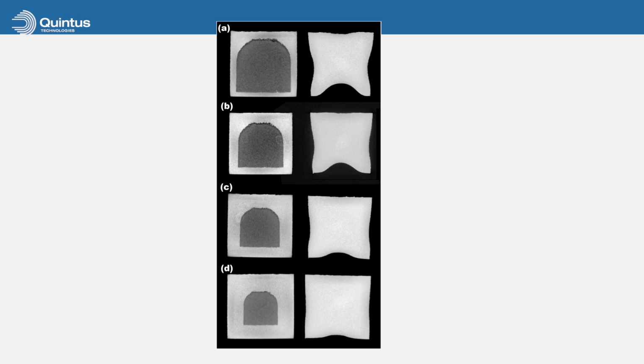This deformation can be predicted by simulation. So some of our team members who are software experts on simulating heat treatment and hipping processes, they made predictions for some coupons, which are basically cubes. So you have like a bloated cube, which is the pre-compensated geometry, which is then manufactured, and then the hipping process then shrinks as it solidifies the internal powder.